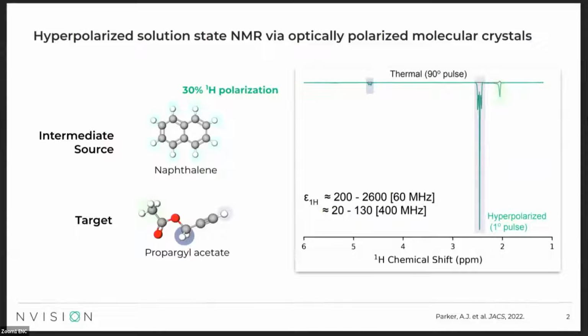We've been working on a technique for producing hyperpolarized NMR spectra based on optically polarized crystals. This is just an example of what our technique can do. Basically we take an intermediate source of polarization, which is highly polarized proton spins on naphthalene molecules. And we can transfer polarization from these proton spins to protons on a target molecule to get a hyperpolarized solution state spectrum of this molecule. This is just one nice example for this molecule, propargyl acetate, which we studied, where you can see we get enhancements of 200 to 2600 over 60 megahertz, or 20 to 130 over 400 megahertz.